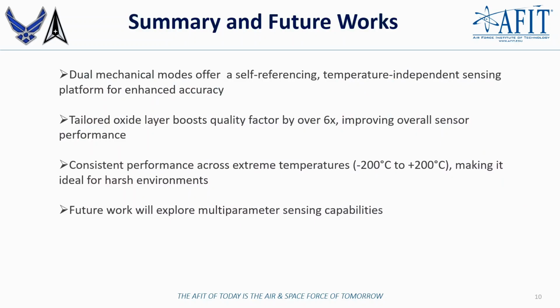So to summarize, our approach leverages dual mechanical modes to provide a self-referencing, temperature-independent sensing platform, which significantly enhances the measurement accuracy. By incorporating the oxide layer, we have achieved more than a 6-fold improvement in quality factor, leading to superior overall sensor performance. And the resonator performs consistently across an extreme temperature range from negative 200 degrees Celsius up to 200 degrees Celsius, making it ideal for application in harsh environments.